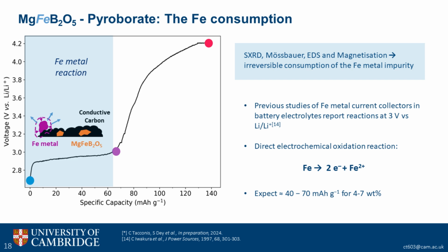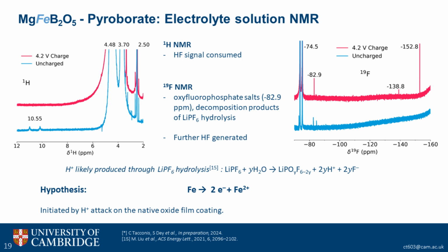So the iron metal is going away, but what's happening to it? We did some solution electrolyte NMR. So what we did was we compared the NMR of the electrolyte when it's just sitting in the glove box with some electrolyte extracted from a coin cell cycled to the end of the first charge. And from the proton NMR, what we can see is that this 10.5 doublet signal, which is the HF, that's present in the electrolyte because of water and the fact that the electrolyte's been sitting there, is consumed throughout the charge. What we also see when looking at 19-fluorine NMR is the presence here in the charged material of oxyfluorophosphate salts, which are associated to LiPF6 hydrolysis, and LiPF6 is the salt that we're using in our lithium-ion electrolyte.